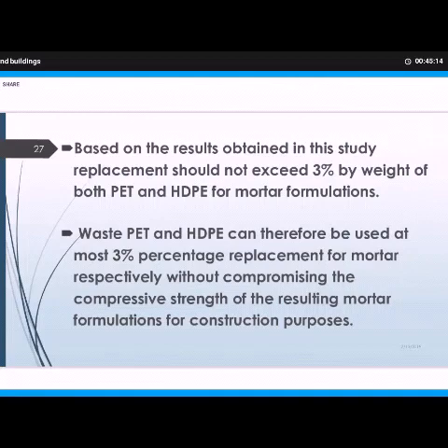Based on the results we obtained, we realized that the percentage replacement should not exceed 3% by weight for both PET and HDPE for mortar formulations, and also waste PET and HDPE can be said to be used, but at most 3% replacement in mortar. And this will not compromise the strength of the resulting mortar for construction purposes.